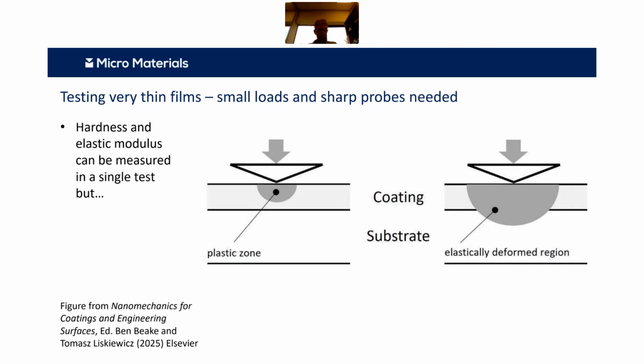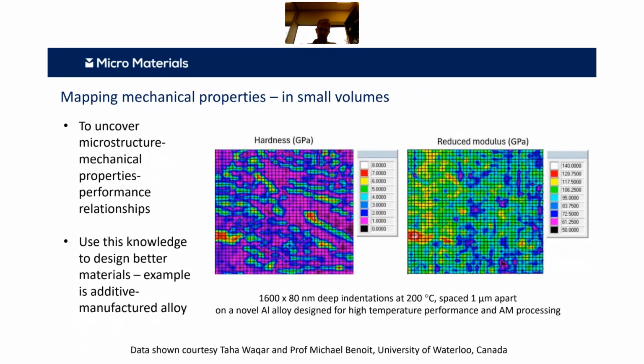But what you're seeing in this, again, if we go back, what we're seeing essentially on the right is because it's coming averaged over a greater area. So with these surface features, the indents are sufficiently small that the plastic stress field is remaining within those surface features, while the elastic map is a little bit more smeared out.